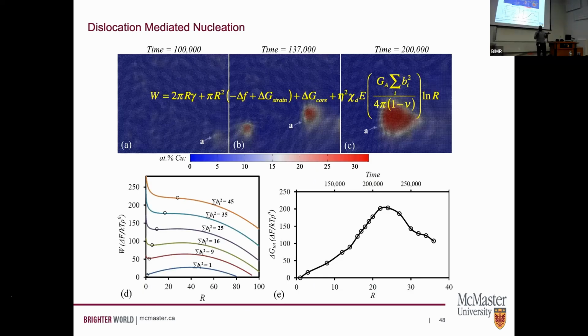So we could actually put some math to that as well. My apologies. What we do is we go to our work of formation, or nucleation statistics. Usually, at least when you teach undergrad, you care about the bulk and the surface, but it turns out that you could also account for strain and dislocation energy, and you could also talk about solute interactions.